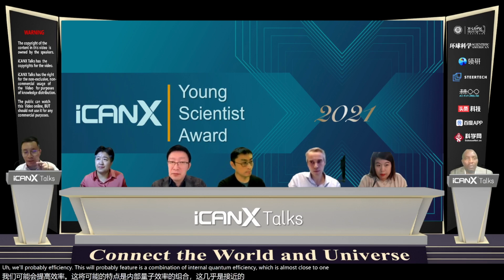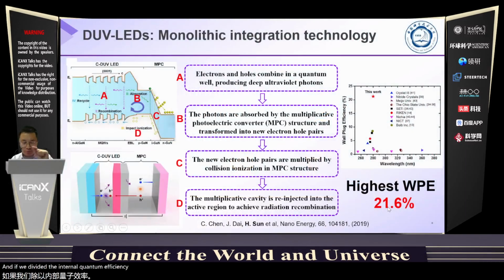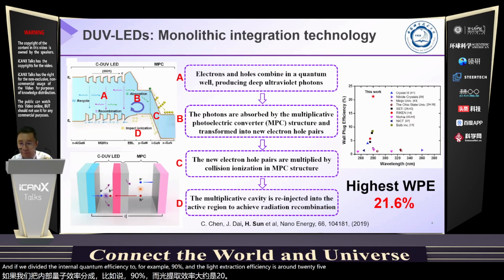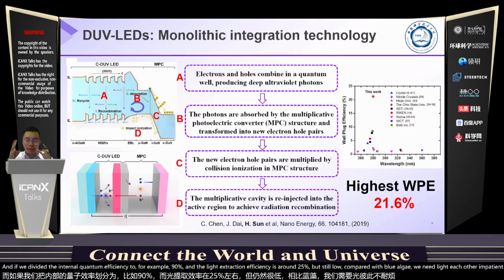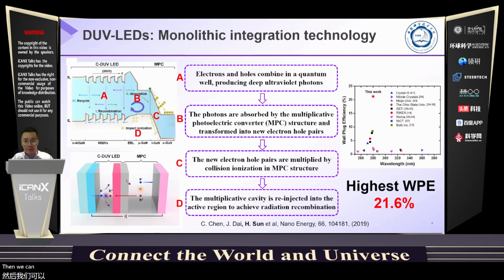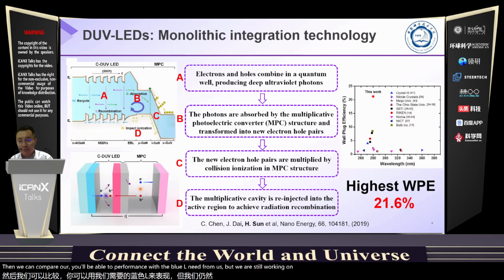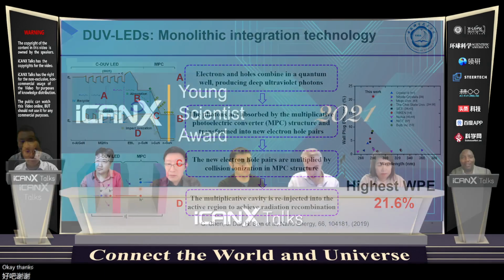This is one of the highest wall plug efficiencies. This wall plug efficiency is a combination of internal quantum efficiency, which is almost close to 1, times the light extraction efficiency. But if we take the internal quantum efficiency as, for example, 90%, and the light extraction efficiency is around 25%, it is still low. Compared with blue LED, we need light extraction efficiency to go beyond 50 or more than 60%. Then we can compare our UV LED performance with the blue LED performance, but we are still working on that. Okay, thanks. Thank you, Miso, thank you very much.